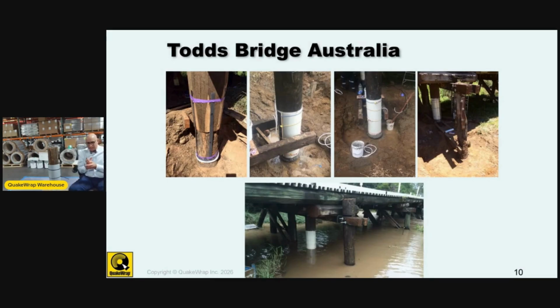One other application is from a job in Australia. Let's say you have a timber pile that you're splicing, so we have a horizontal or seated cut, and we need to bring back the flexural capacity of the pile at that region. In this case, we are adding some carbon laminates to the side of the pile, and then we wrap the PileMedic laminate around it, and that whole area gets resin injected. Not only do you get the flexural capacity of the jacket because you have glued it with that epoxy resin to the pile, but you also engage all of those carbon strips embedded in the annular space because they are now all epoxied together. That gives you a lot of additional flexural capacity also.